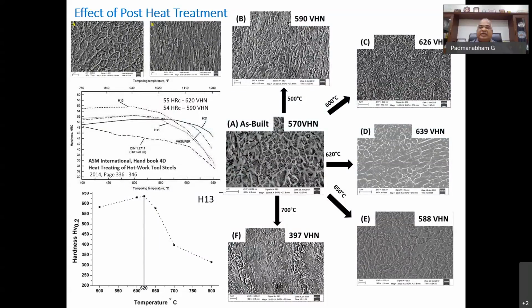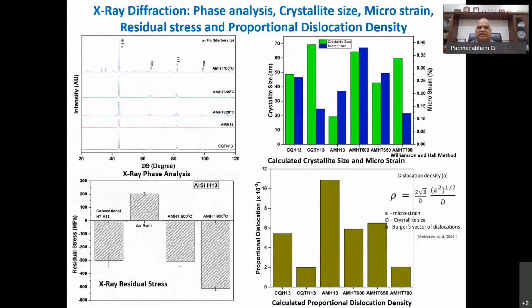We are able to achieve this: just build a tool or the part and just give a 620 degrees centigrade treatment, and then you have broken the cast structure and also retained the carbides that are required in the grains as well as at the grain boundaries, giving you the high temperature properties. A very detailed metallurgical analysis of phase analysis was done, and using X-ray residual stress measurement methods, the crystallite sizes and the microstrains have been calculated. And using these values, using the equation on the bottom, we calculated theoretically how much dislocation density is there in different heat treated conditions.